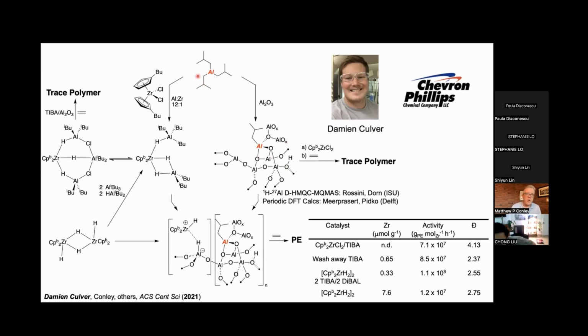On the other side of the coin, we have excess TIBA in solution, enough that we passivate all the OHs on the alumina surface, and there's still enough TIBA left to react with the metallocene, which upon mixing and walking down to the NMR spectrometer converts to a mixture of two different hydride products. This product shown here was characterized by Brintzinger and Bercaw about 15 or 20 years ago as the reaction product of this metallocene with DIBAL. So if we selectively make this hydride react with our TIBA functionalized alumina, we also don't get polymer.